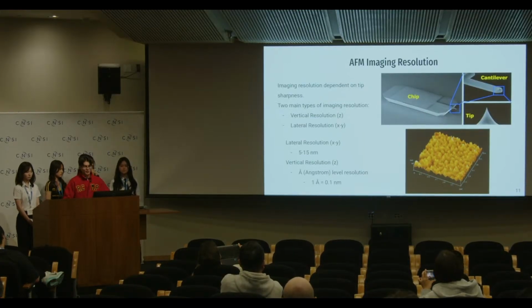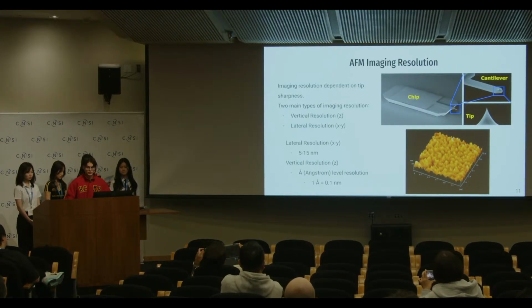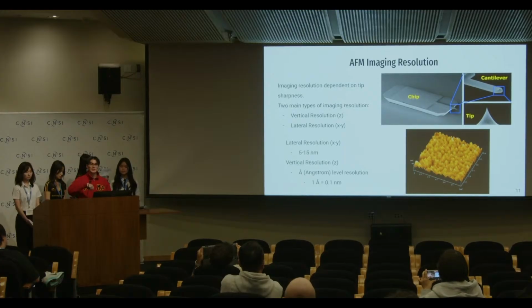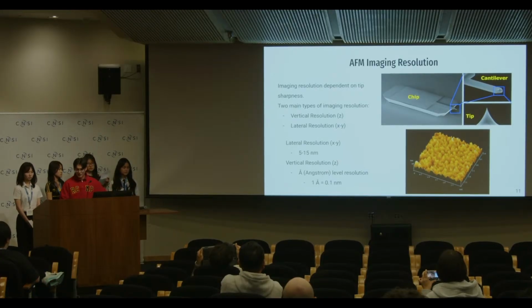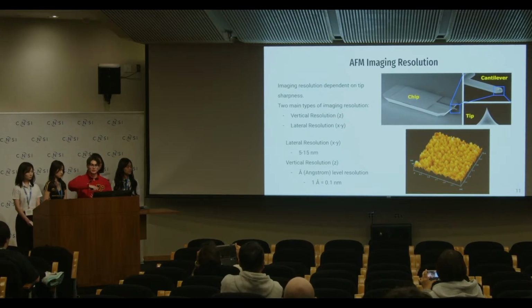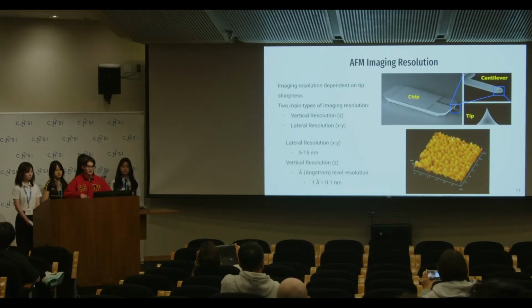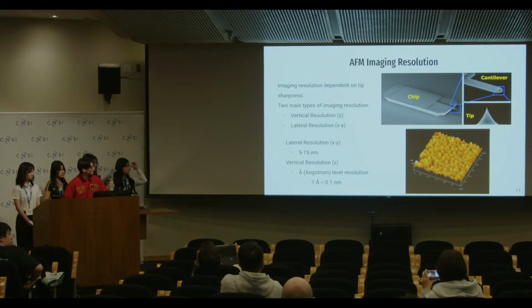And then AFM imaging resolution. The imaging resolution is very dependent on how sharp the tip is. Usually these tips are ideally one atom at the bottom. It can usually be a little off, but mostly it's just a couple atoms wide. And then for AFM, we have two main types of imaging resolution. We have vertical resolution, which is the z-axis, and then lateral resolution, which is just the flat 2D image. So lateral resolution is mainly between 5 to 15 nanometers, and then vertical resolution is a lot more precise. It can get down to angstrom level, which is fractions of nanometers.